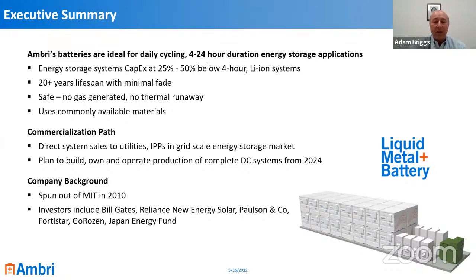It's a very strong safety aspect to this technology. So it does not have a thermal runaway mechanism. And that's because the technology does not generate gas inside the cell under any circumstances. Typical circumstances where other batteries will generate gas is when they're short-circuited or overcharged or over-discharged. So this battery chemistry doesn't generate gas under those circumstances, so it does not increase pressure and then increase temperature and pressure and temperature until ultimately other battery chemistries need to vent off either hydrogen or organic solvent like lithium ion. So it avoids the most typical safety risks associated with lithium ion batteries.